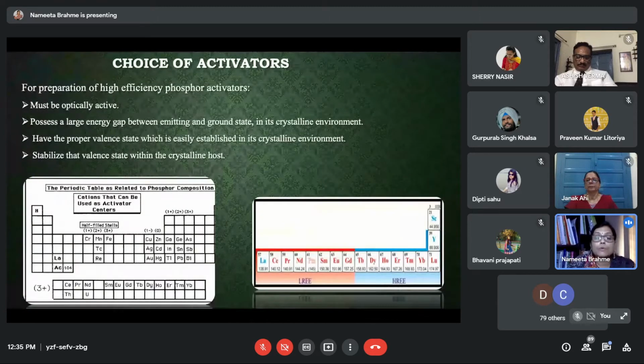So to do this, what kind of cation do we have to use? We have to choose a cation whose electronic ground state has no uncoupled spins, no angular momentum, and in which the sum of all electron momenta, J, capital J, is also zero, so that the perturbation by localized phonon modes of the host lattice is non-existent. This mandates the choice of activators with the 1S0 ground state. There are no other choices. The other factor is that it must be optically active, so that the emission comes from the activator site.